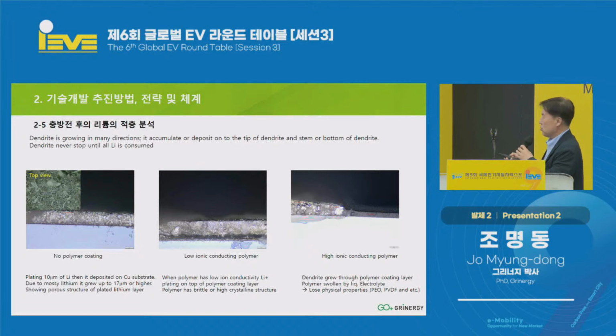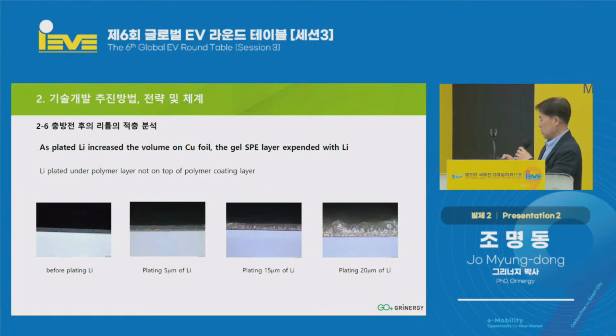So as dendrite keeps forming, once again, the cathode and anode will be separated. So this is the system that we have applied, and we try to check it out. As you can see, we checked the effect of preventing direct contact with electrolyte when applied as a protective film. Lithium plated under the polymer layer, not on top of the polymer coating layer, and the polymer layer protects lithium metal from direct contact with the lithium electrolyte. It goes below that, and dendrites are well covered.